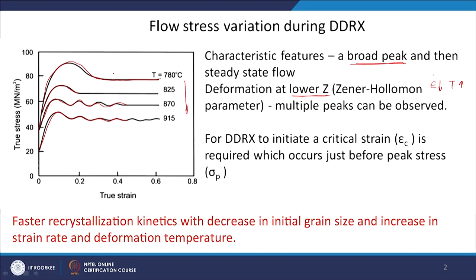For discontinuous dynamic recrystallization to initiate we will require some critical strain. I can define a critical strain just before the peak stress. Peak stress is where the slope of this particular curve is zero. The dynamic recrystallization must have started somewhere at that point, but we are not sure which strain that is right now. We will find out how to determine that critical strain.